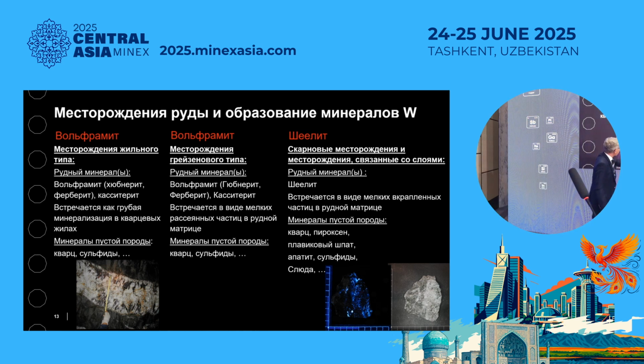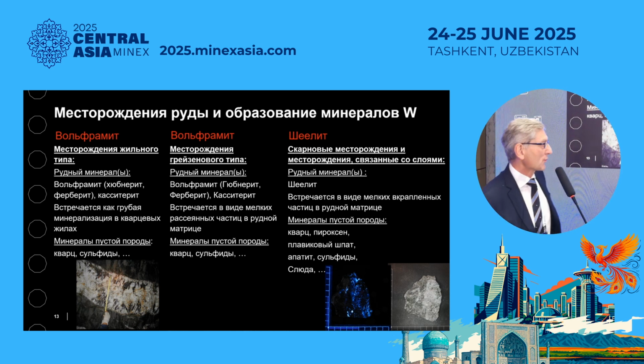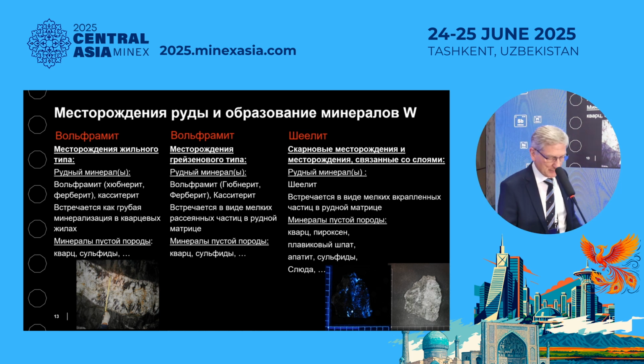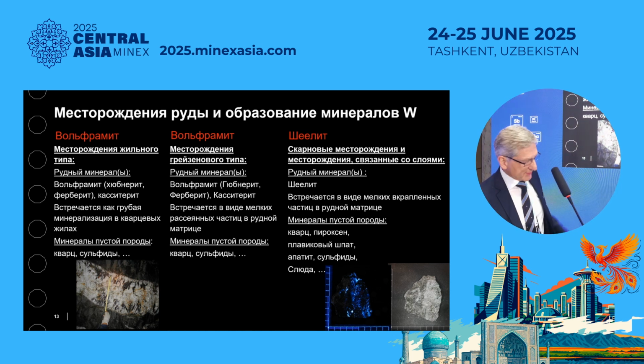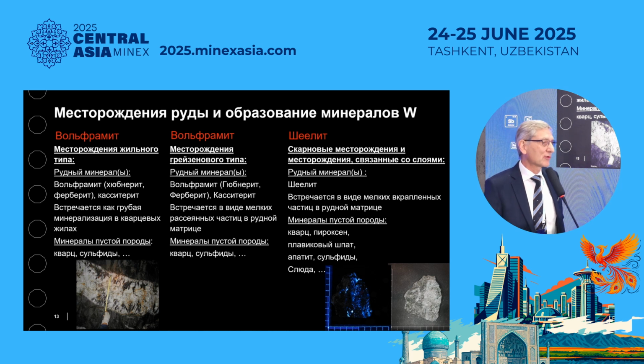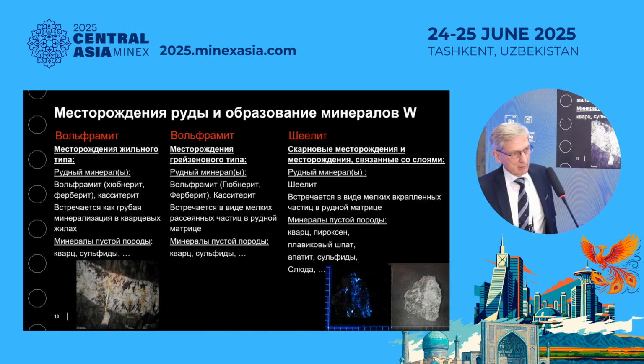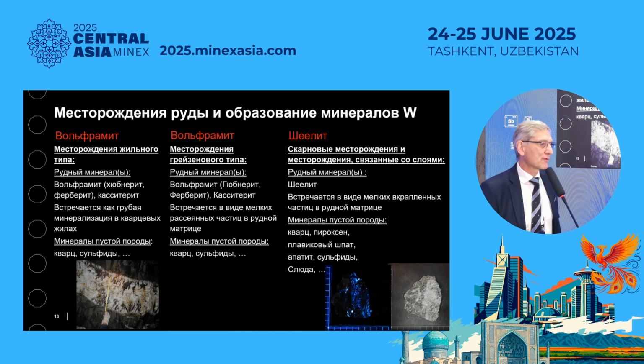Here on the bottom, you see a vein-type deposit, yeah, and these black needles you see here, these are the wolframite crystals, so tungsten is very coarse here. So these are the vein-type deposits. A bit more difficult it gets when you go to Greisen, which are tungsten mineralizations in silicate rocks. And here the wolframite is very finely intergrown and causes some issues with the concentration. You can apply different techniques, but for sure flotation is very difficult to achieve here.